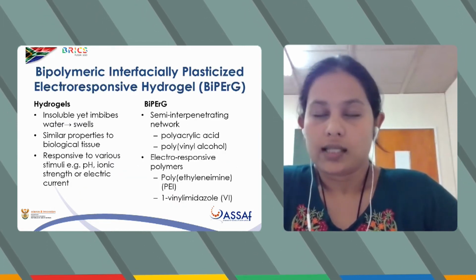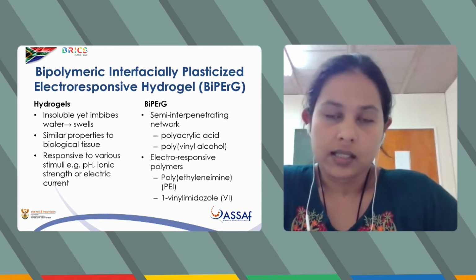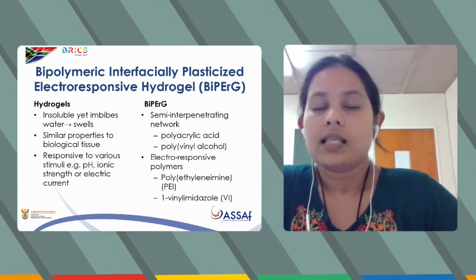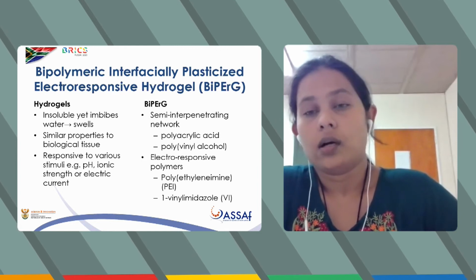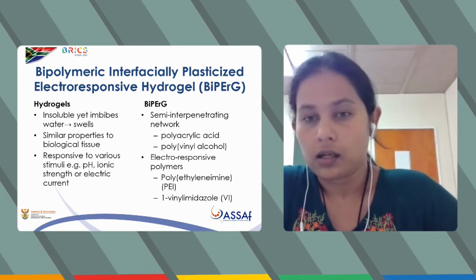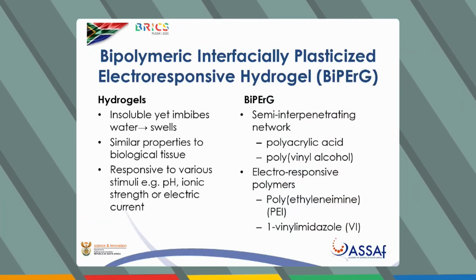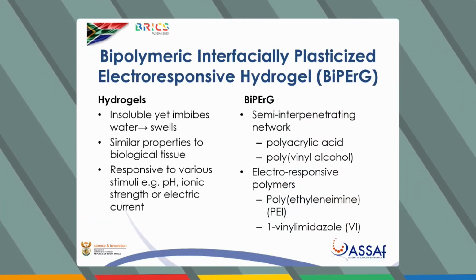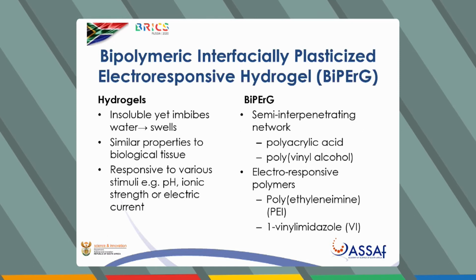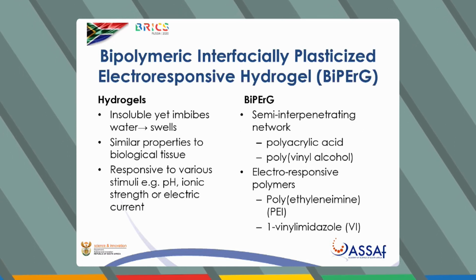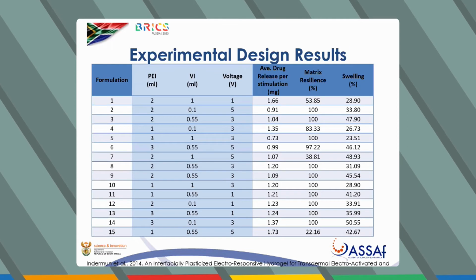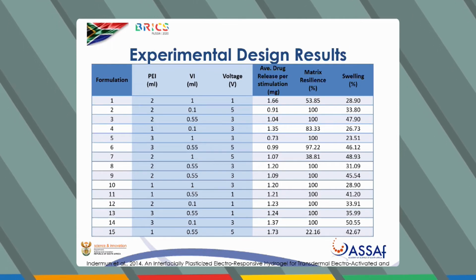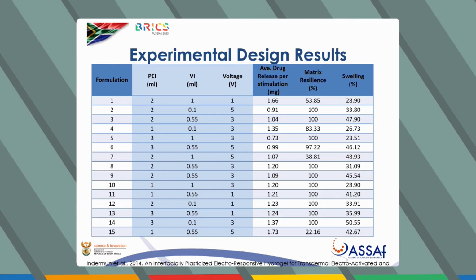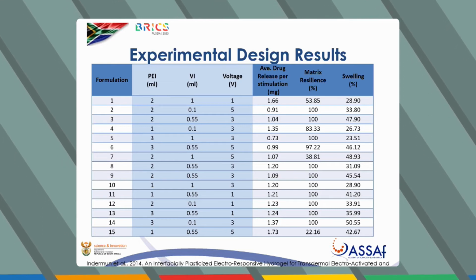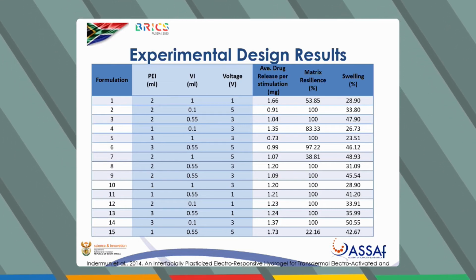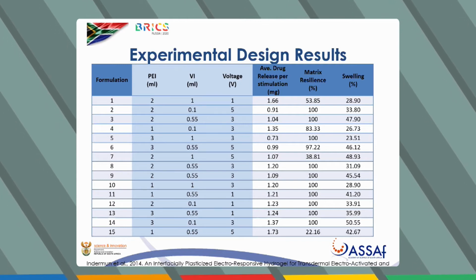So a hydrogel was used as the drug delivery system for the listed reasons, and it was synthesized to consist of a semi-interpenetrating network of polyacrylic acid as well as polyvinyl alcohol. In this network, I incorporated polyethylene imine as well as 1-vinyl imidazole as the electroresponsive polymer blend. I used a Box-Behnken experimental design model to optimize the BiPERG, and it consisted of 3 variables: the polyethylene imine amount, the vinyl imidazole amount, as well as an applied voltage.